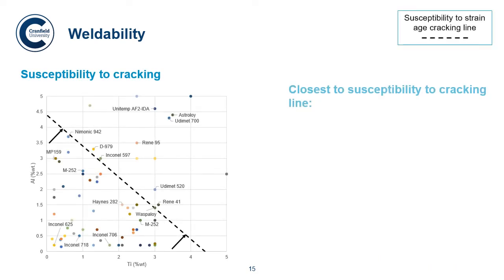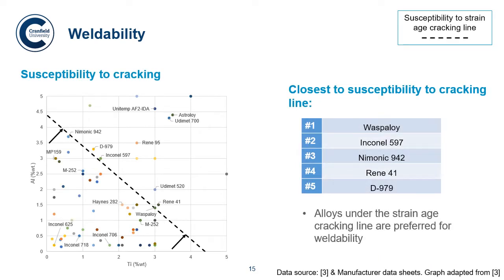So then we look to the weldability of the alloys to rank the alloys in their susceptibility to cracking. To start with, you can see this dotted black line, which is representing our susceptibility to strain-age cracking line. Everything above this line is going to be more susceptible to strain-age cracking, and everything below the line is going to be less susceptible and hence more weldable. So we rank them on their distance from the line. Alloys under the strain-age cracking line are preferred for weldability concerns.